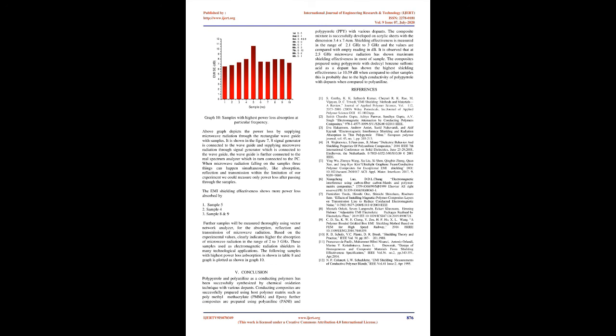Shielding effectiveness is measured in the range of 2.1 GHz to 3 GHz and the values are compared with the empty reading in dB. It is observed that 2.5 GHz microwave radiation has shown maximum shielding effectiveness in most of the samples. The composites prepared using polypyrrole with dodecylbenzene sulfonic acid as a dopant have shown the highest shielding effectiveness, that is 10.59 dB, compared to other samples. This is probably due to the high conductivity of polypyrrole with dopants compared to polyaniline.